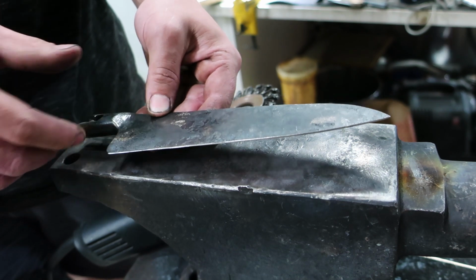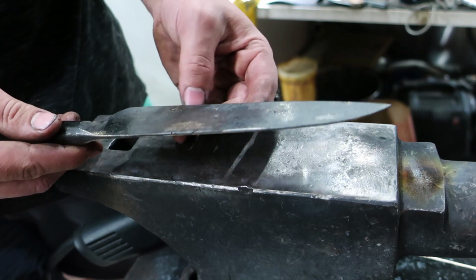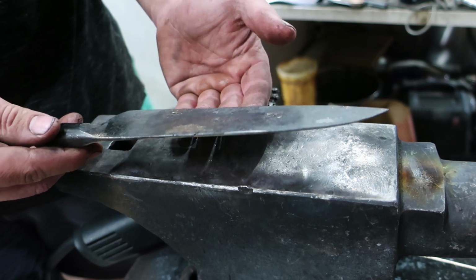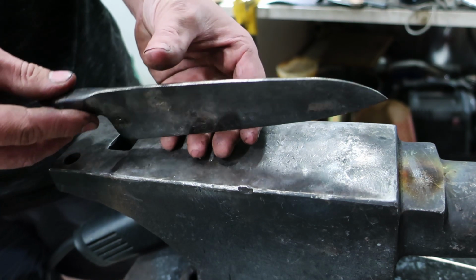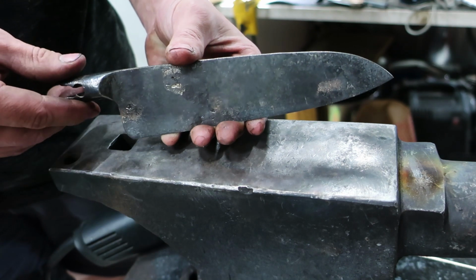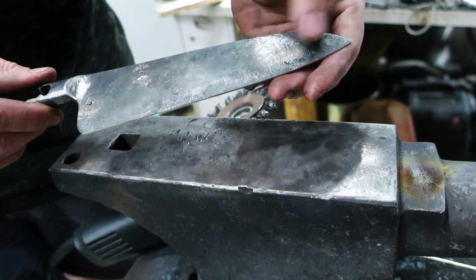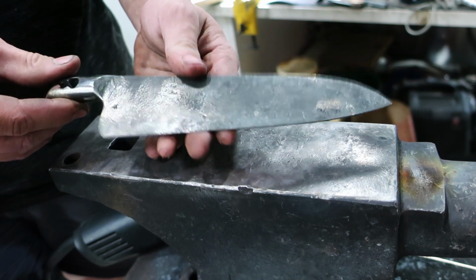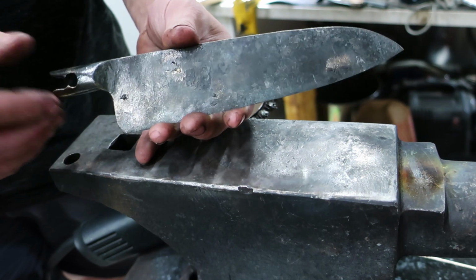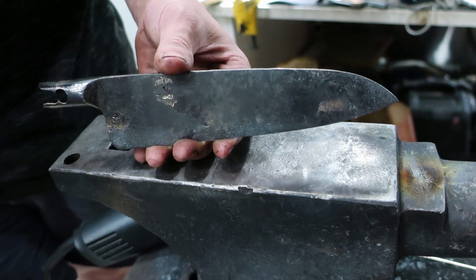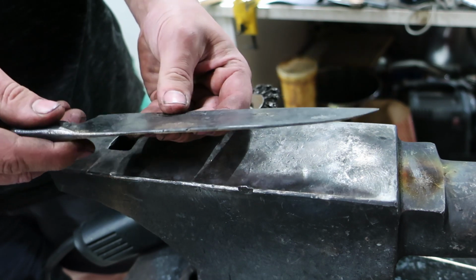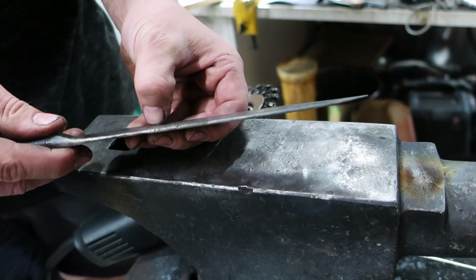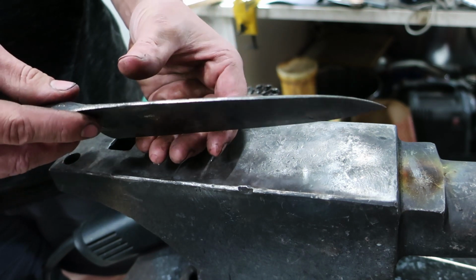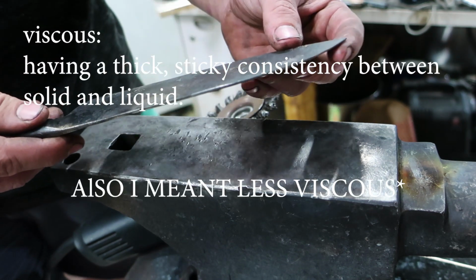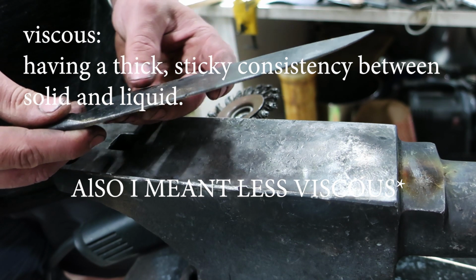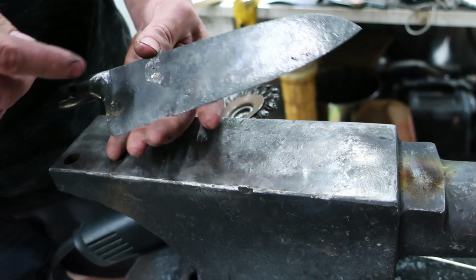The site I bought the 26C3 from is GFS Knife Supplies. They recommend between 800 to 820 degrees Celsius and a fast quench oil. So I set my kiln up to 820 degrees using Houghton K as the quench medium. The alternative is Parks 50, and I always normalise 3 times or more depending on how many times I need to check for warp in the blade before quenching. Also, I preheat the oil to make the oil less viscous, which makes the oil easier to flow and agitate, and hopefully the distortion will be minimal.